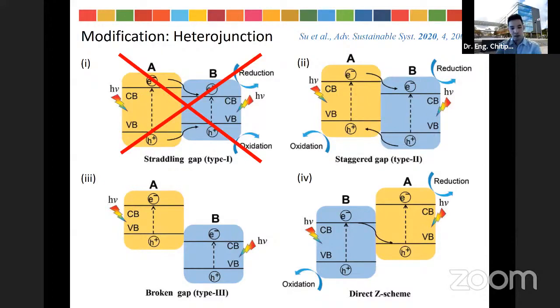In type 2, the conduction band level of material A is higher than the conduction band of material B. The valence band level of material A is also higher than the valence band top of material B. This type is called the staggered type of heterojunction. Under light irradiation, electrons are excited in both materials. The electron can move from the conduction band of material A to the conduction band of material B, and the hole of material B can migrate to the valence band of material A. The electron can accumulate in the conduction band of material B, and the hole will accumulate in the valence band of material A, resulting in enhanced charge separation and avoiding the recombination of the charge carriers by using this junction.